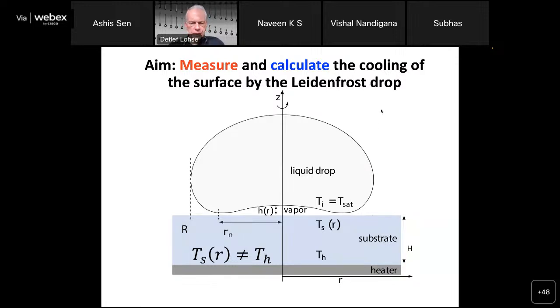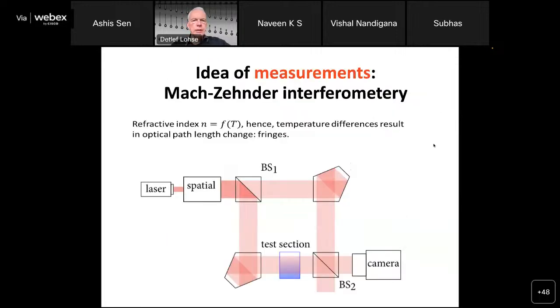He can't measure it dynamically, but what he did is that he put a droplet in, so to say, a static Leidenfrost droplet. He had a droplet fixed above the substrate and would feed the droplet in a way that the loss by evaporation is compensated by influx of this droplet. So he has a quasi-static situation, and with this he has enough time to measure. So indeed my pessimism was justified with respect to the dynamical measurements, but my pessimism was not justified with respect to static measurements, and Michiel van Limbeek really did a wonderful job in measuring this, as you will see in a second. So this is a quasi-static case, and the heat conductivity then is given there. The liquid droplet has the temperature here at the saturation temperature, and we have some vapor layer in between. And Michiel's idea was to use Mach-Zehnder interferometry.